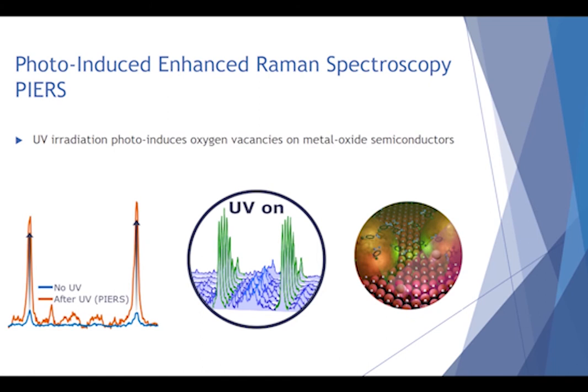Pre-irradiating with UV light causes oxygen vacancies to form on the surface of these metal oxide semiconductors. The oxygen vacancies then interact with analyte molecules, enhancing the Raman signal beyond the surface enhanced Raman signal that was there before, or the SERS signal. You can track the formation of vacancies by tracking the steady increase of the Raman signal over time.